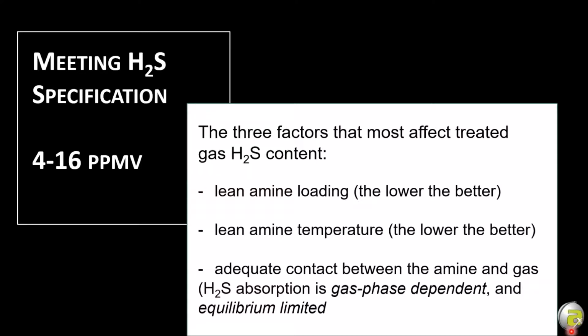And the third and final one is an obvious one. We have to have good contact between the amine and the gas that travels up the contactor. We tend to say that H2S is equilibrium limited. The reason for that is, if you can recall from our December session, we said that amines react instantaneously with H2S. So kinetics are not really that important. Well, they're obviously always important in a chemical reaction, but they're not limiting to us because the reaction is instantaneous. So we want good contact. The tower has to be functioning.